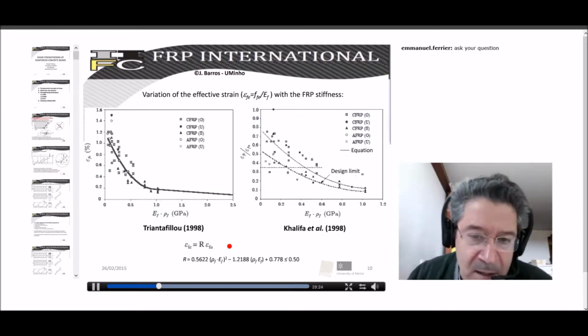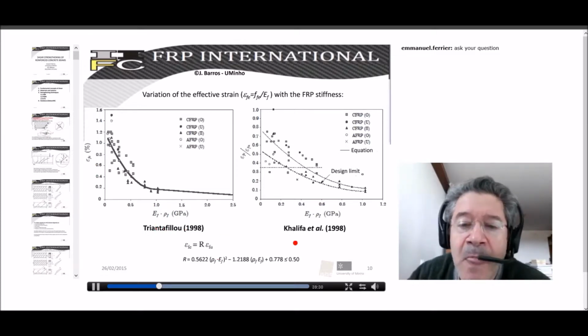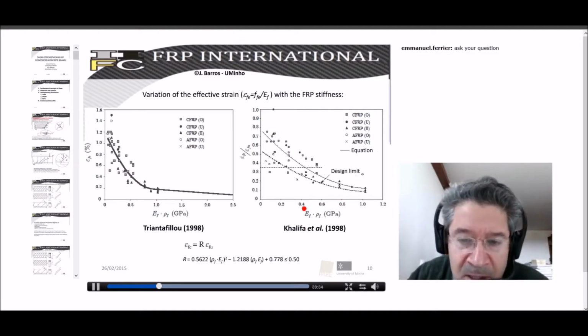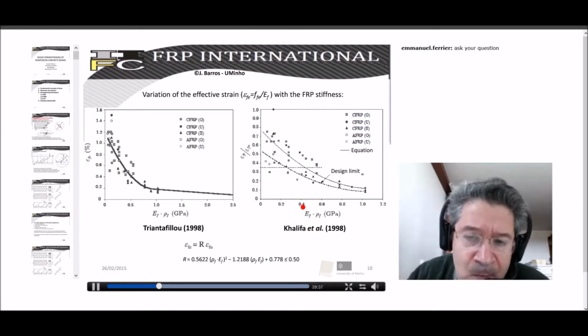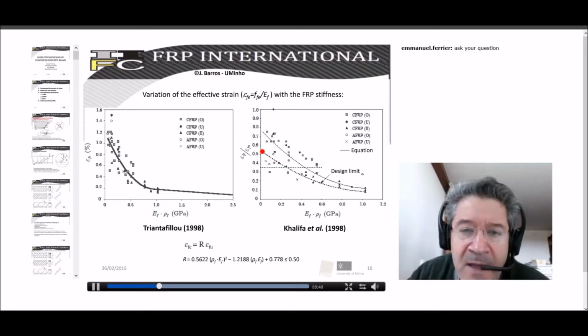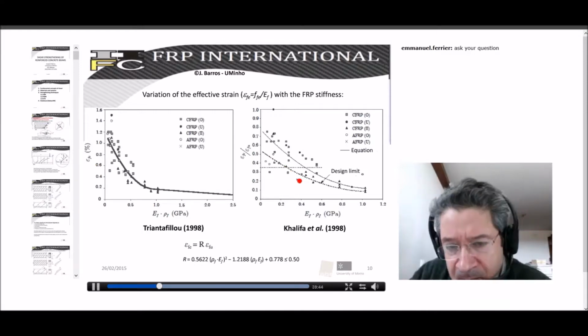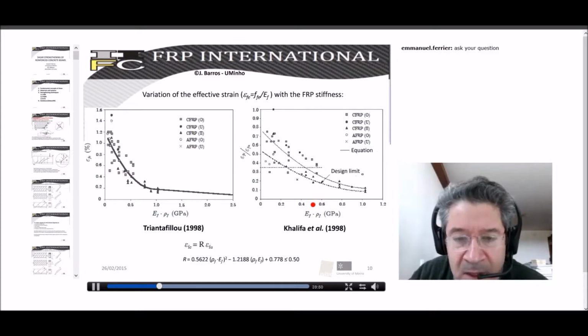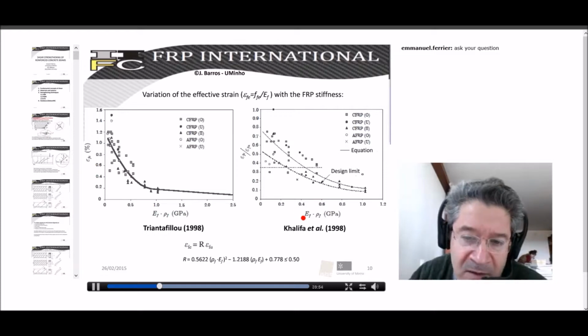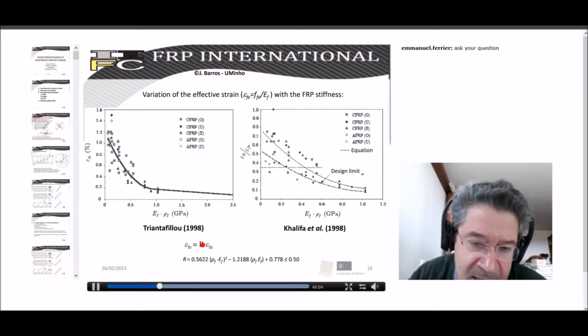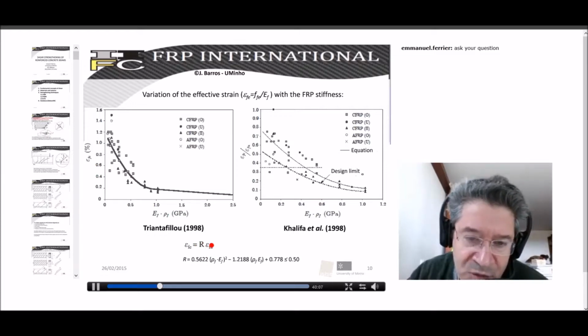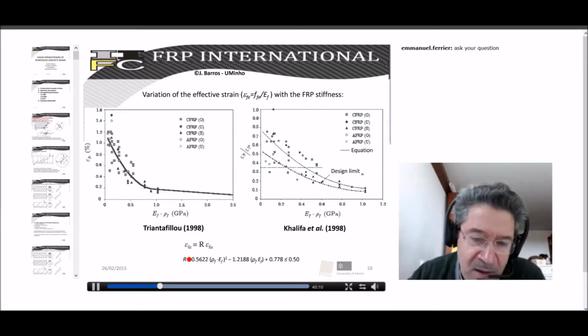Well, this data was obtained by Professor Triantafillou some years ago, and this data is obtained by Khalifa, but we, in fact, are Khalifa's co-authors. But in fact, we see a clear tendency for a decrease of the effective tensile strain with the increase of the stiffness of these FRP systems. And it was proposed this equation that evaluates the R parameter, and then R is multiplied by the ultimate strain, and then we can have an estimation of the effective strain.